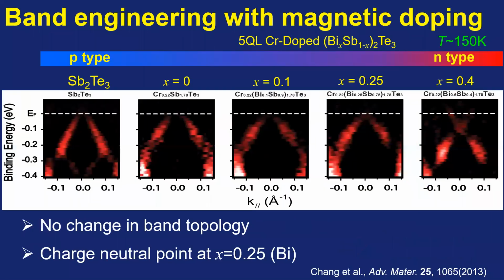Let's see chromium-doped bismuth antimony telluride. This is the upper band of the 5 quintuple layer chromium-doped bismuth antimony telluride. This is the band structure of antimony telluride. It's P-doped. The Dirac point is above the chemical potential. When we dope some chromium inside, it's a little bit more hole-doped.